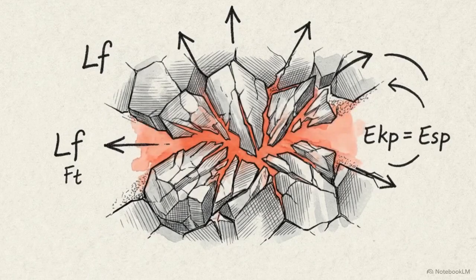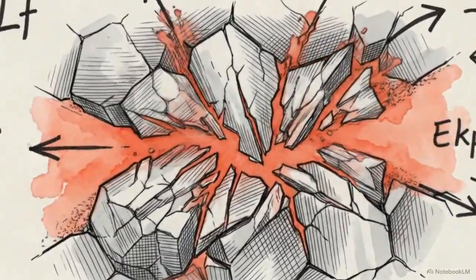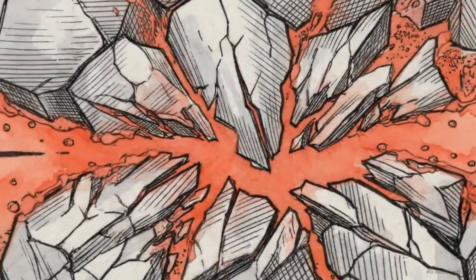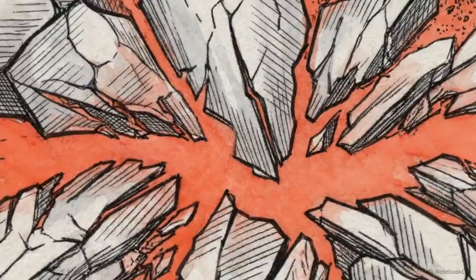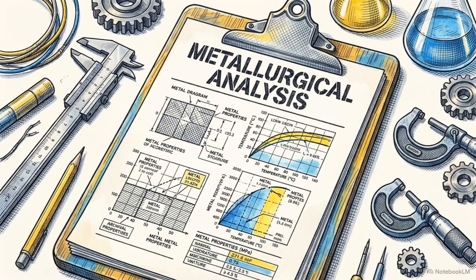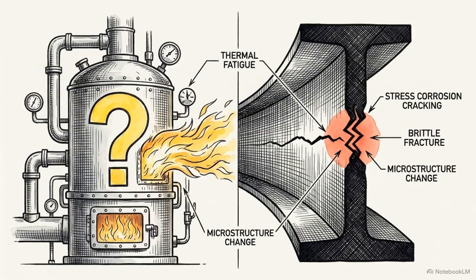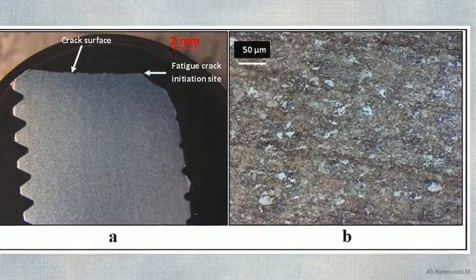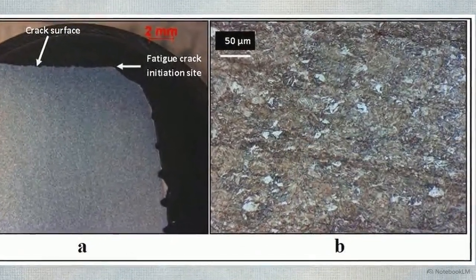Rebuilding the exact stress state at the moment of failure requires deconstructing the fracture mechanics down to the microscopic level. Before analyzing the mechanics, we must eliminate variables in the steel itself. We need to confirm whether improper heat treatment or a bad material batch compromised the fastener metallurgy. This micrograph shows the crystalline structure of the broken grade 5 fasteners.